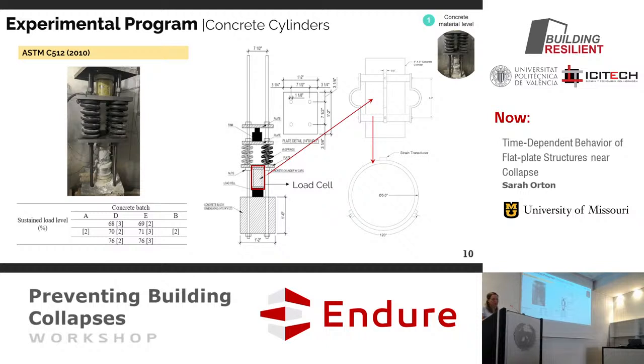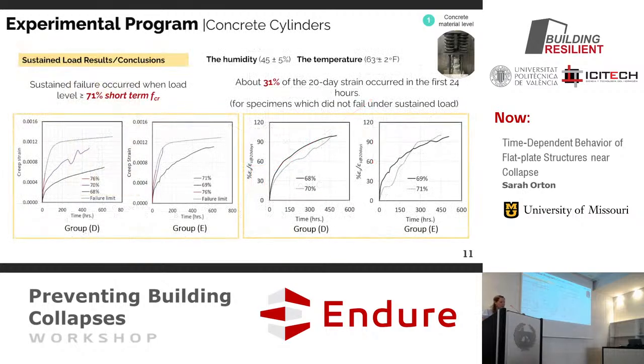So we did some of our own compression tests. There's a cylinder in here, put on some strain gauges to amplify the strain, put it under some nice big thick springs to create a sustained load, run the tests. And for our cylinders, what we saw is if we had a sustained load greater than about 71%, we reached failure. These were the same concrete that I was using in my test structure. It was a scaled concrete, so the aggregate size is about half the normal aggregate size. And so that may be why it was a little bit less.